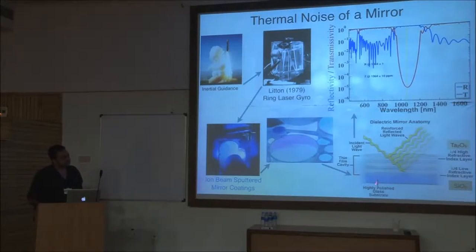And they look something like this, look like thin film things. And this is the diagram of what goes on inside of them. Here's this substrate made of glass and on top of that you put some higher index material but it has an index of a fraction between 2 and 3 or so. And then you can put some low index, high index and so on. And there's a well-known property that if you make them have a quarter wave in terms of the optical path length, then you can get a very high reflectivity stack.